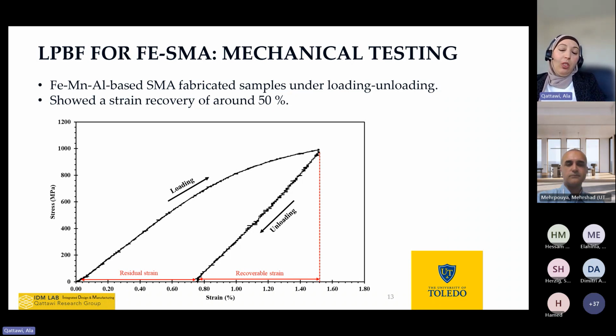Now, when we talk about good recovery, that's not the optimized one. Hopefully, when we reach the point where we completely understand the effective processing parameters, and we spot this small, tiny window where we have no problems, no defects, good track morphology, good microstructure, and so on, then this is the area we need to optimize. But initially, the alloy system showed promising strain recovery of around 50% between loading and unloading.